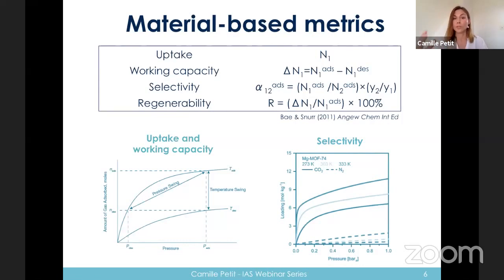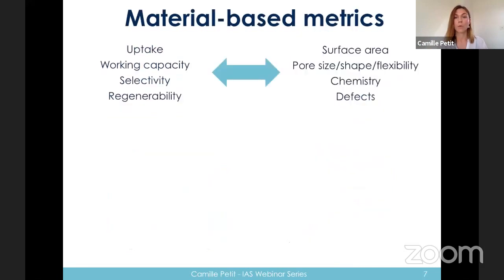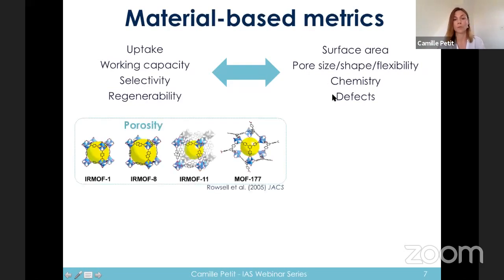So all those materials-based metrics are somewhat linked to the chemistry and the structure of our adsorbent. So we have direct links to some extent between uptake, working capacity, selectivity, and regenerability, and surface area, pore size and shape and flexibility, chemistry and defects. So if we think, for instance, of porosity, we have here a series of metal organic frameworks, or MOFs, and you see that they have different pore size, different pore shape, and that will, of course, influence your adsorption process.